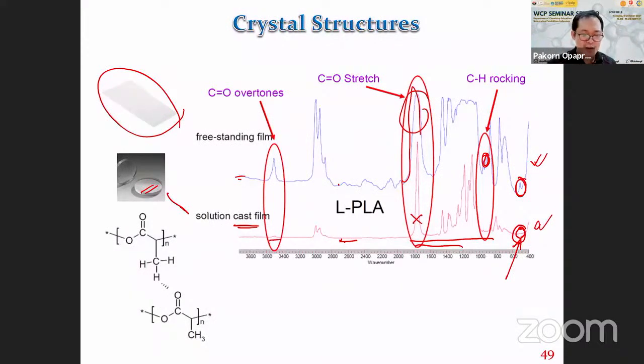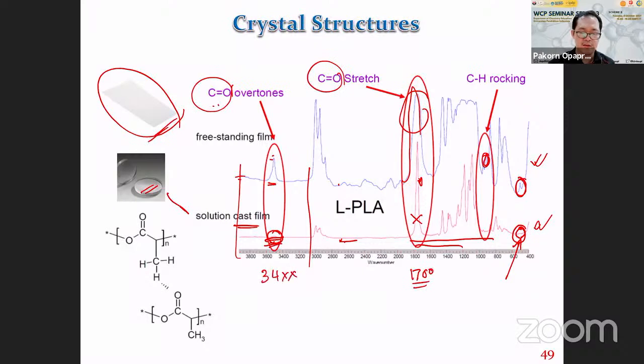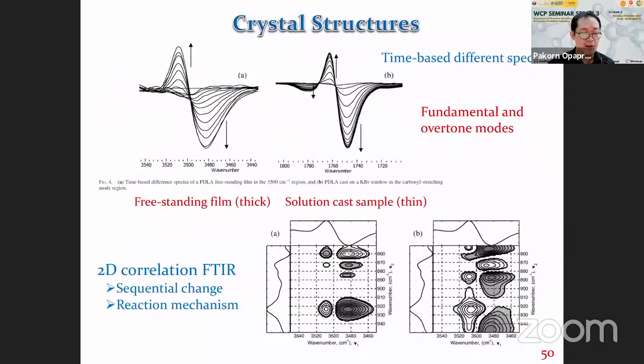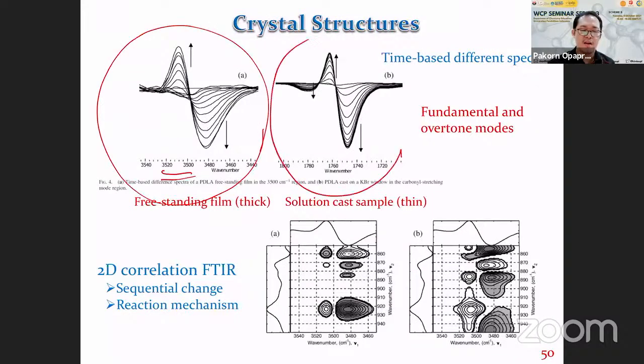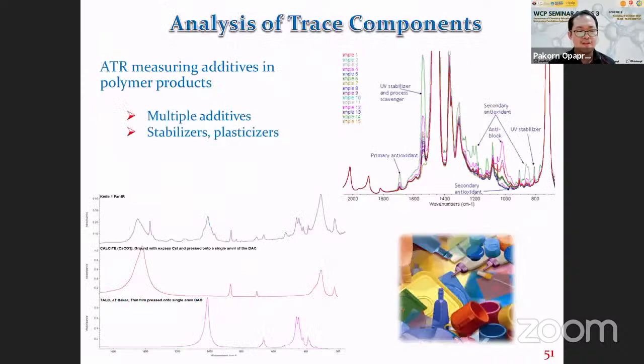And also, if you look right here that I mentioned, this area is also the area for overtone combination mode as well. So the overtone combination mode here can be very weak. If you want to get information, we need to have a thick sample, so this becomes a bigger peak. Actually, this is similar to this peak. This is the overtone of carbonyl group. Carbonyl group is at 1700 something, and this is 2 times, which is around 3400 something. So we can get the same information either from here or from here. If we look here, the information from 3500 and 1700 show the same behavior. So these are some strategies that we can play with to get information from infrared spectroscopy.